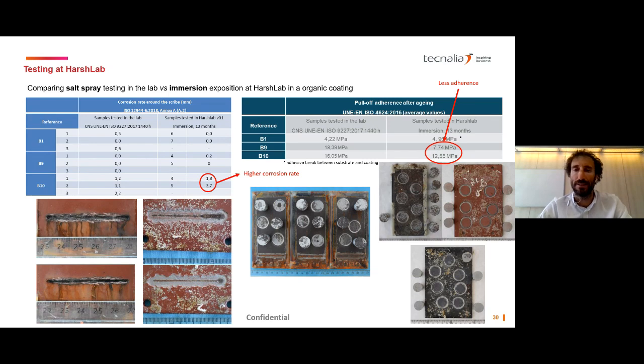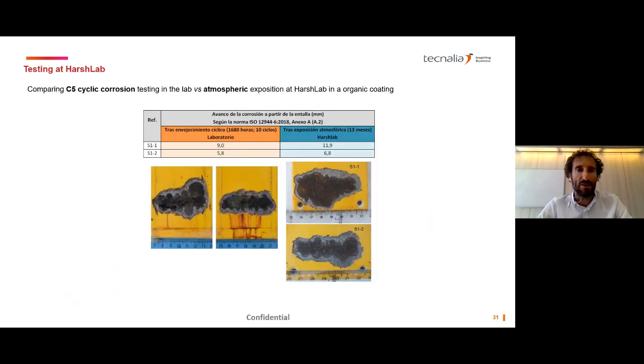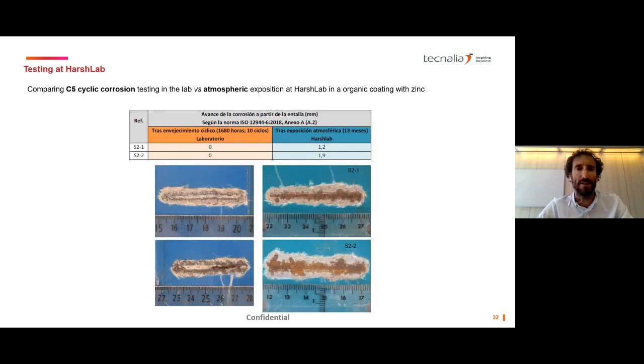to break the coating. This is a comparison of a C5 cycling corrosion test in the lab versus atmospheric exposition at HarshLab. Again, 1,600 hours in the lab, 10 cycles according to NORSOK, against 13 months in HarshLab. Again, much higher corrosion is detected in the offshore conditions. And this last one is a C5 cycling corrosion test against atmospheric exposition in organic coating with zinc. In the lab, no corrosion was observed, while in the HarshLab, yes, we observed appreciable corrosion.